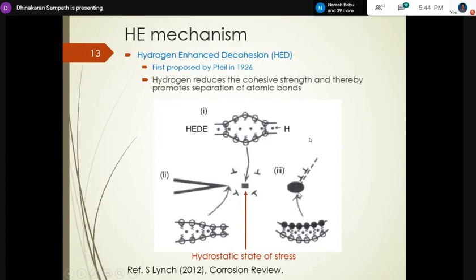And in the case of some obstacles, some second phase particles, when dislocations create a stress concentration or stress intensity there, hydrogen goes there, and between the second phase atoms and matrix atoms, because of the hydrogen, it just unzips and leads to a crack. So this is the very early model. This is not experimentally proved, because one has to see at the atomic scale. Only simulations are there.